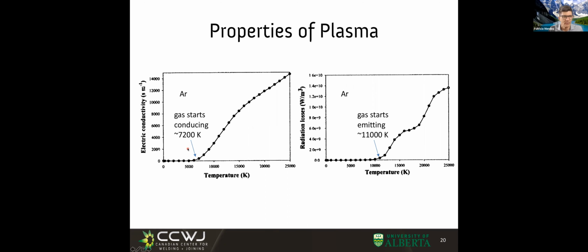We see that at low temperatures, room temperature would be right here, electrical conductivity is 0. And that is what keeps us safe when we walk next to an electrical outlet. When we heat it to about 7,200 Kelvin, conductivity starts. And the hotter we are, the more conductive it is. Of course, the hotter we are, the more electrons are going to be loose, and my electrical carrying capacity is higher.